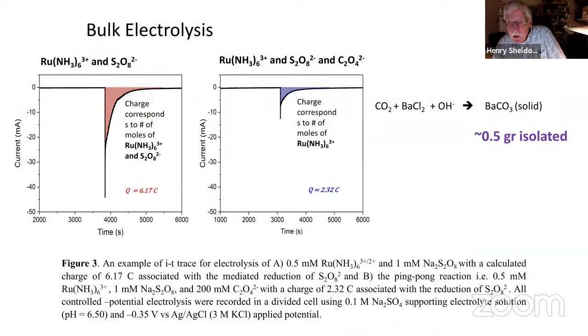We also do bulk electrolysis because this is more convincing. And so what we're doing is preparing here a solution of ruthenium hexamine and peroxydisulfate. And we apply a potential where the ruthenium hexamine is reduced and then this persulfate is catalytically reduced. And you measure the electrolysis curve, current versus time. The area under that curve, this red shaded area, corresponds, using Faraday's law, to the number of moles of ruthenium hexamine and persulfate that you added to the solution, just as it should.